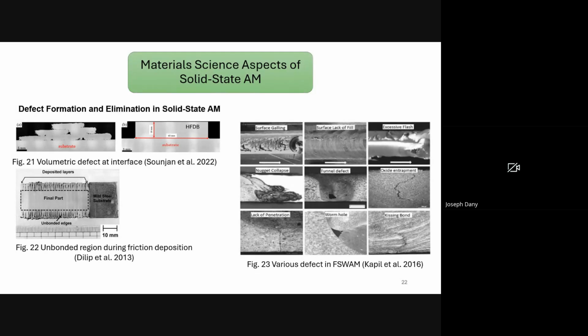Volumetric defects include unbonded regions or voids inside the deposited or joined material volume. These voids or unbonded regions degrade mechanical performance and require machining to remove. In solid-state additive manufacturing by friction-based methods, improper material flow or insufficient bonding energy causes these defects. Other defects in FSW-based solid-state additive manufacturing arise mainly due to incorrect parameter settings such as tool rotation speed, welding traverse speed, tool tilt, plunge depth, and force.